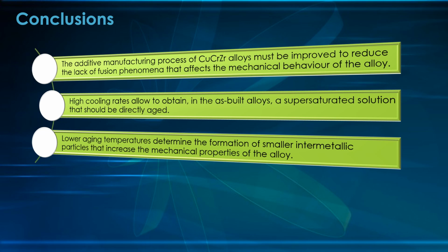And the results of the aging tests allowed to see that lower aging temperature determine the formation of smaller intermetallic particles that are able to increase the mechanical properties of the alloy.